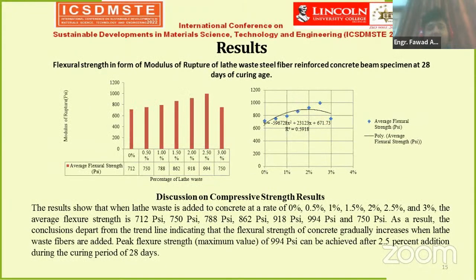Now, this is the modulus of rupture or flexure strength of the beam specimens. Here you can see that the modulus of rupture also follows the same trend line as followed for compressive strength for 7, 14, and 28 days. This also shows that 2.5% is the optimum dosage of lathe waste steel fibers in concrete. After increasing beyond 2.5%, the strength decreases.